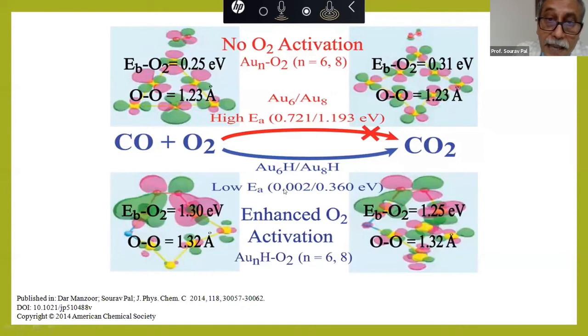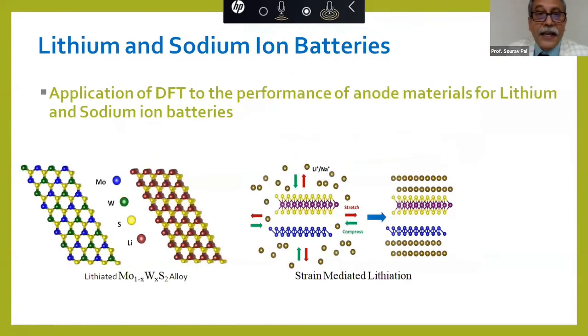If you look at the entire barrier, it's very instructive to see that with Au6, you have a 0.721 eV barrier. With Au8, you have 1.193 eV. But as soon as you do hydrogen chemisorption, this almost becomes barrierless. And even here, the barrier drops out. So one atom, and this is the very interesting part of cluster catalysis, that is just a simple single atom. Putting a simple single atom changes everything.